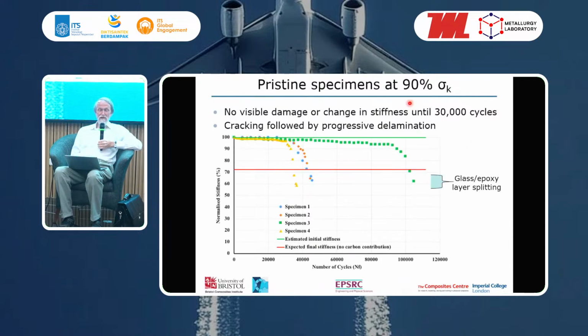Then the load was increased up to 90% of the knee point strain, and initially there's no visible damage or change in stiffness until after about 30,000 cycles. Then we start to see in some specimens a reduction in stiffness, and this one here goes right up to about 100,000 before we see a significant drop in stiffness.